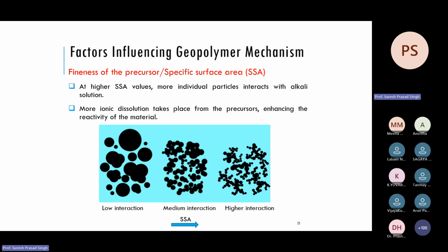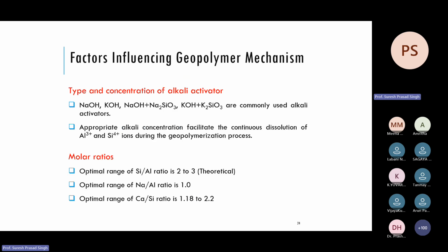This is very common, because to have a high strength of cement, it should be ultrafine cement, since strength is a surface thing. Then the type and concentration of alkali. Normally you use sodium hydroxide, potassium hydroxide, sodium silicate, potassium silicate, or a combination of these. Use silicate in conjunction with the alkali material because sometimes we find that the silica to alumina ratio, which should be 2 to 3, is not obtained from the source material. Whatever source material like fly ash or slag we are using, if the silica ratio is less, then to supplement that silica we use sodium silicate.